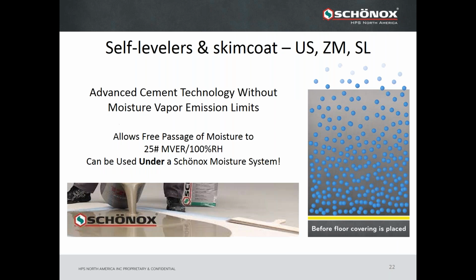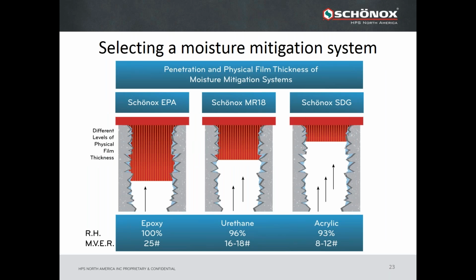The great news is that Schönox can assist you with our cementitious technology in our self-levelers and our feather edge products. Our US and ZM are self-levelers. Our SL is a feather edge product. They contain advanced cement technology without moisture vapor emission limits, meaning they can allow free passage through our underlayments all the way to 100% RH without any failure. In fact, they can even be used underneath an epoxy moisture mitigation system because of the high tolerance of moisture they provide. So they're equipped to cover any need that you have in your moisture reading.